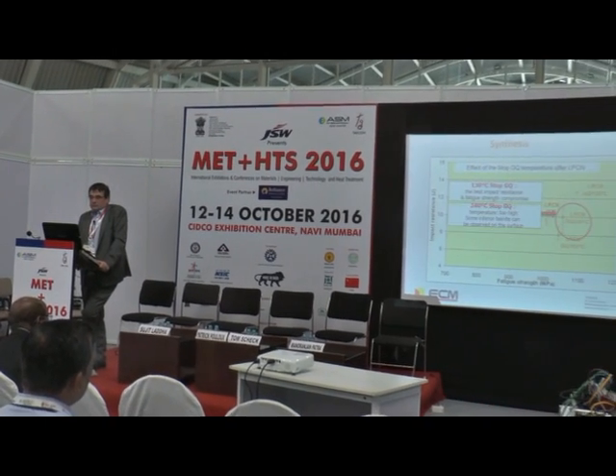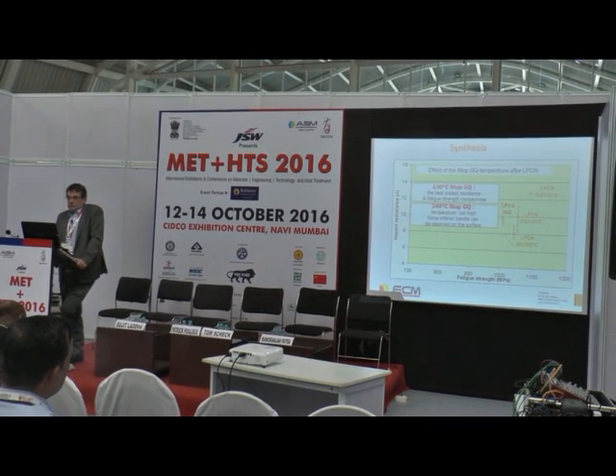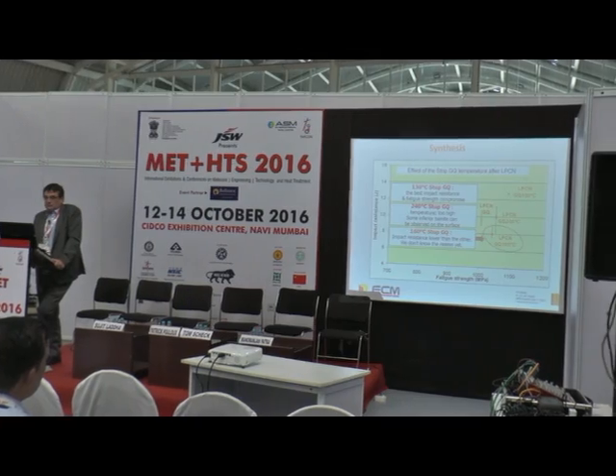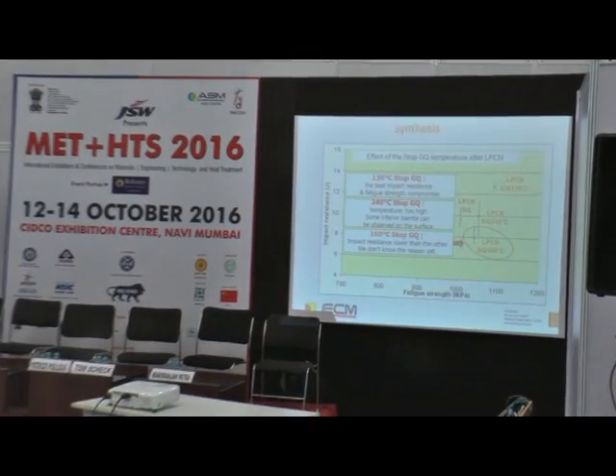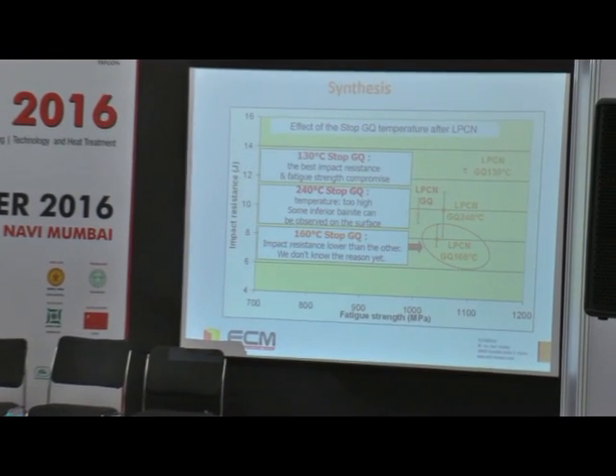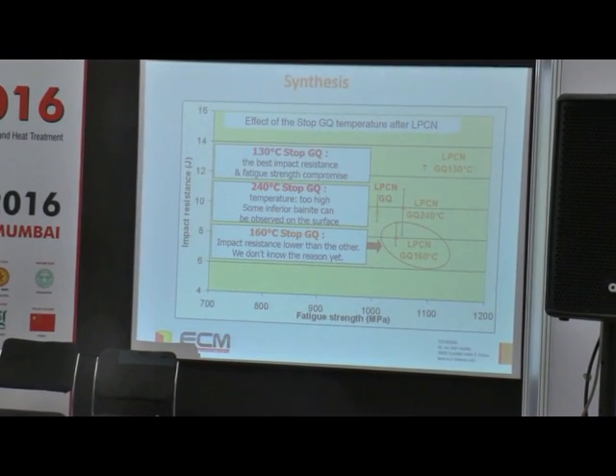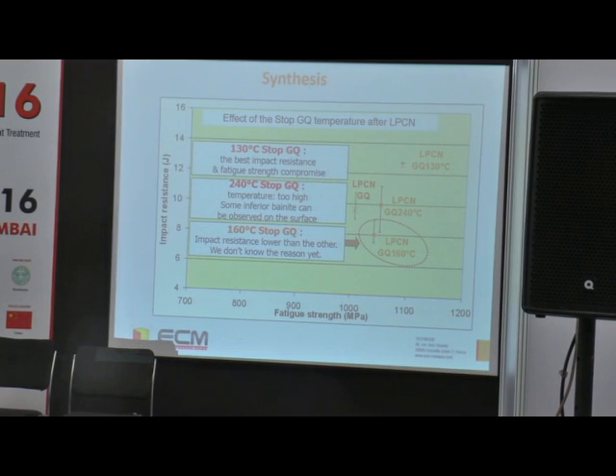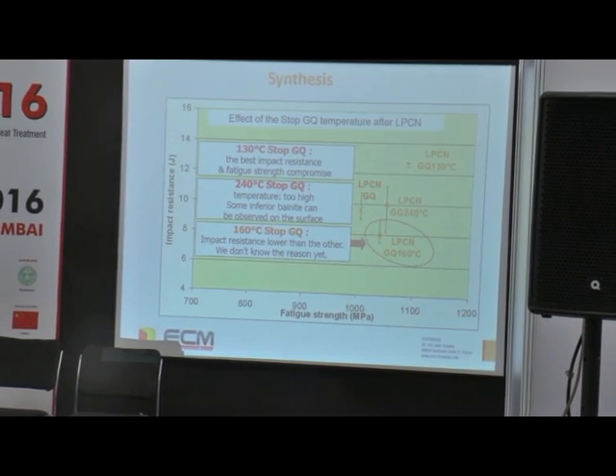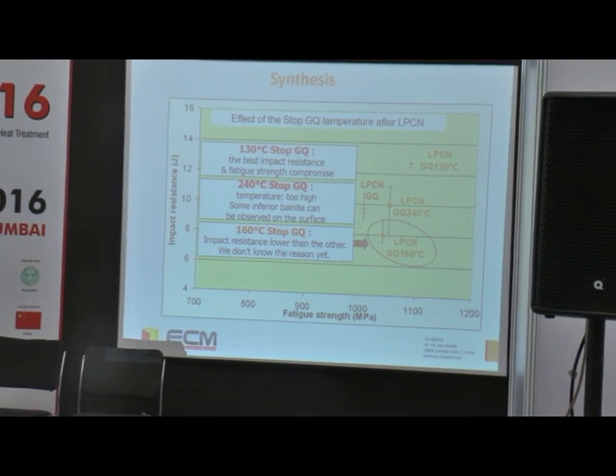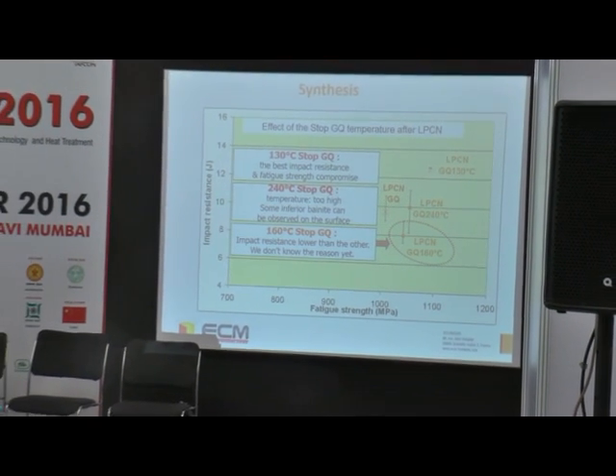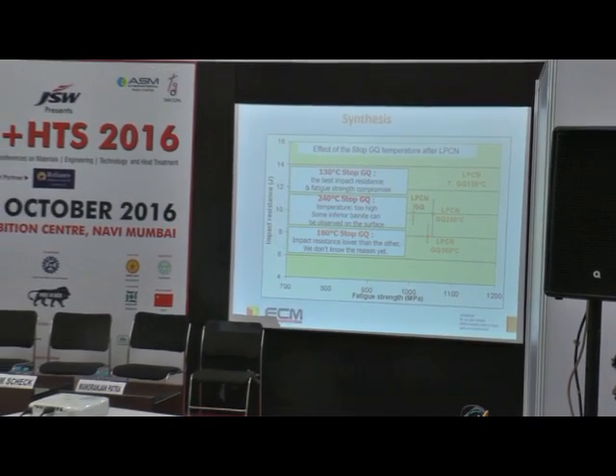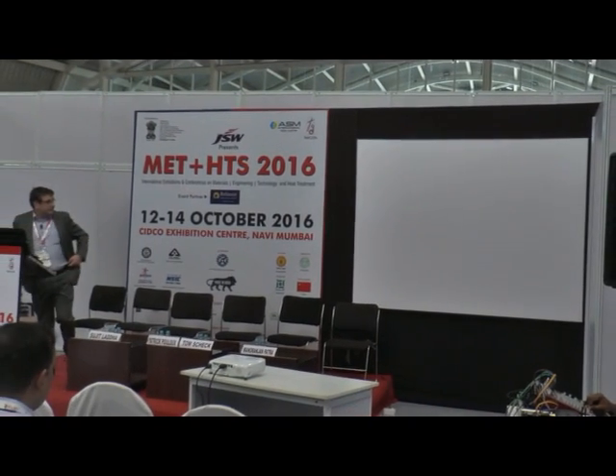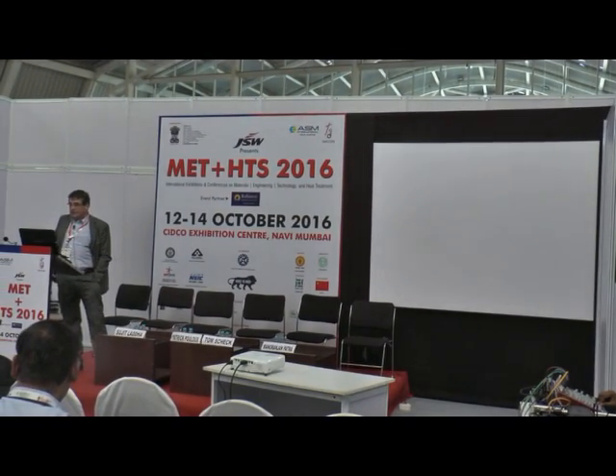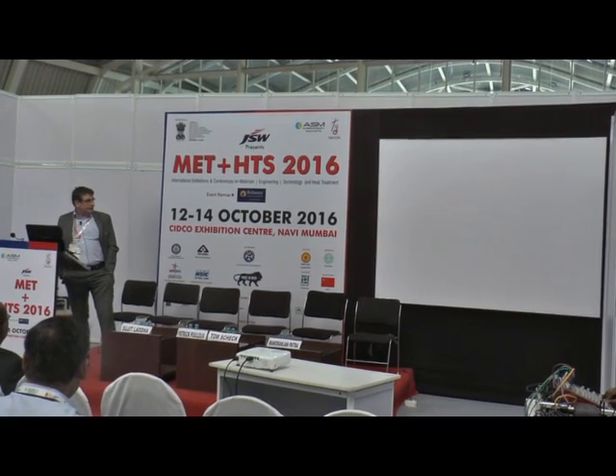The reason for that is that at 240 we have lower bainite on the surface, which reduces the impact resistance. But at 160 we have an even lower result, which was not explained.